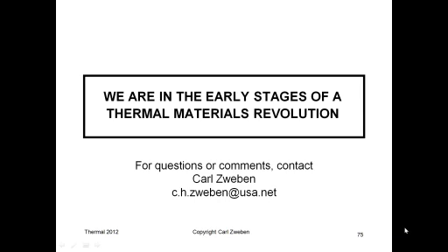But I did have a question at first here concerning some of the materials that were discussed. For example, the flexible graphite have low through thickness thermal conductivities. How would you deal with this? The first thing to do is use an anisotropic finite element model or other analytical model that incorporates anisotropy to determine whether the through thickness and in-plane properties of the materials as it exists are adequate, and you may find that they are. If they're not, there are tricks you can use, like incorporation of thermal vias.